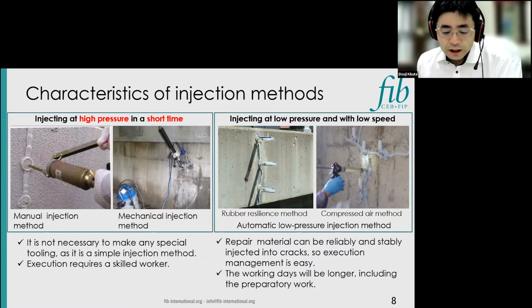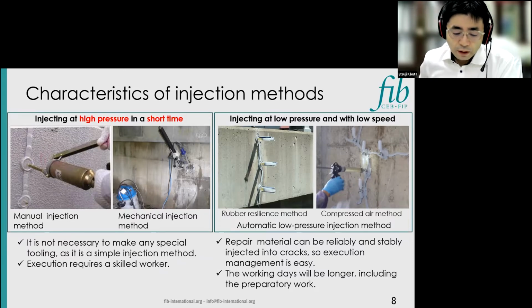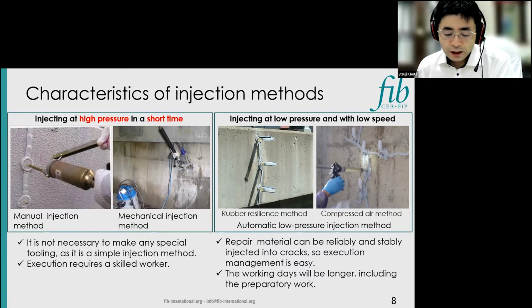The automatic low-pressure injection method enables reliable and stable injection. So, execution management is easy. A special tool is required, but after filling the tool with injection materials, no manpower is required. Because of the low pressure, there is little leakage from the seal and no skilled worker is required. But the working days tend to be longer, including the preparatory work.